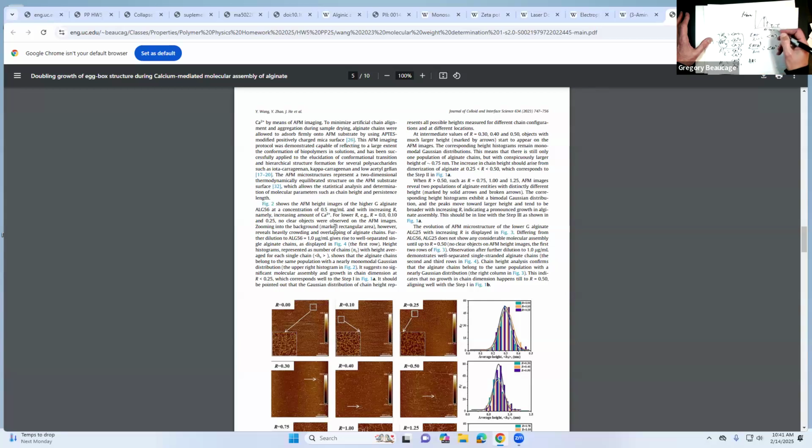Then if you want to know about the distribution, well, how wide is the distribution? You take the MW divided by MN. That's called the polydispersity index. So he takes MW over MN, and I was expecting 2. That would be the normal number you'd expect. Polyethylene, when you buy it, is 16. And if you make an anionic polymerization that makes monodispersed, that's 1. Okay, so when you look in this paper, his number is 1.3 or 1.2, which is pretty narrow.